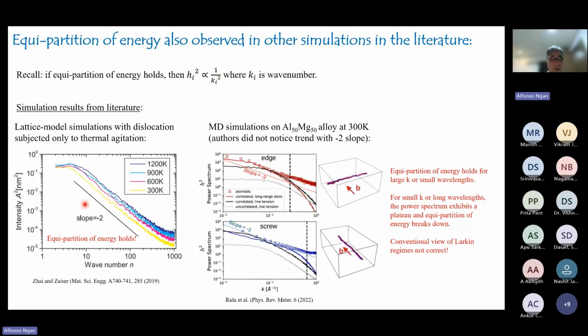So for example, in this reference, again from CCAs, but those are high temperature simulations, if you look at the h squared versus the k, or the wave number, you do have a big regime where the slope is -2. So in this case, it's not -3, but it's -2. Obviously in this case it's due to the thermal contribution, but in this other reference, this -2 slope was also observed. So we were not the only group to observe this equipartition of energy.